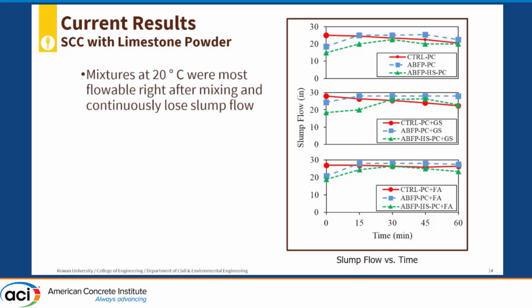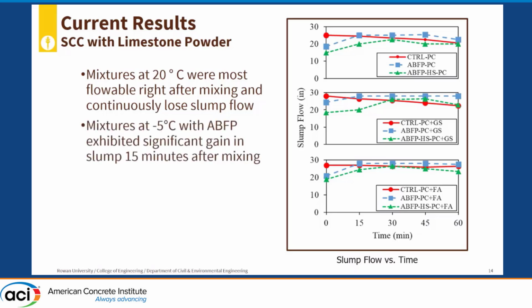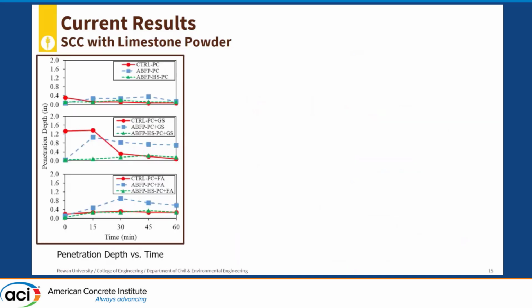So our observations: mixtures at 20 degrees Celsius were most flowable right after mixing, and then they continuously lose workability with time. For the blue ones, which are the mixtures at -5 degrees Celsius with ABFP only, they have lower workability right after mixing, increased workability after 15 minutes, and then retain it until the end of the 60 minutes. When added with hydration stabilizer, or the green ones, they needed 30 minutes to achieve the maximum flowability, and however, adding hydration stabilizer also promotes earlier slump loss.